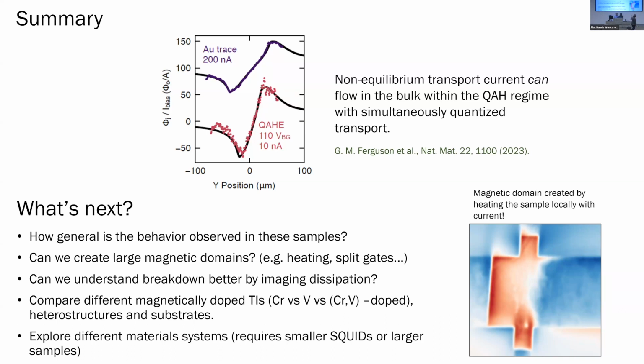The orbital magnetism that's not modulated by me applying a varying transport current should be part of what I see in the DC channel. But in these systems, there are also real magnetic moments and real magnetization coming from ordered magnetic moments. So you can't easily disentangle what is orbital magnetization and what is just ferromagnetism.